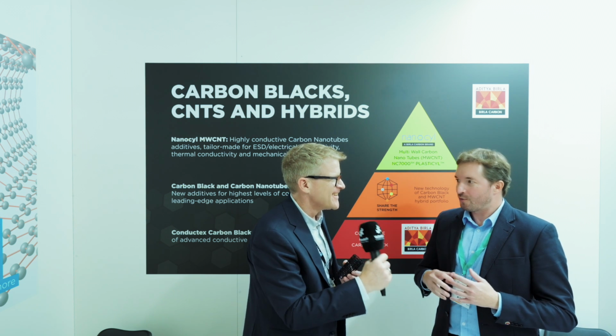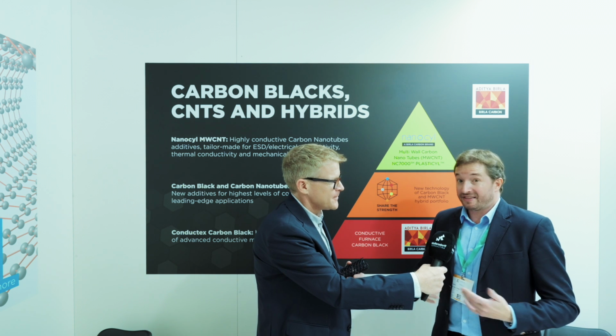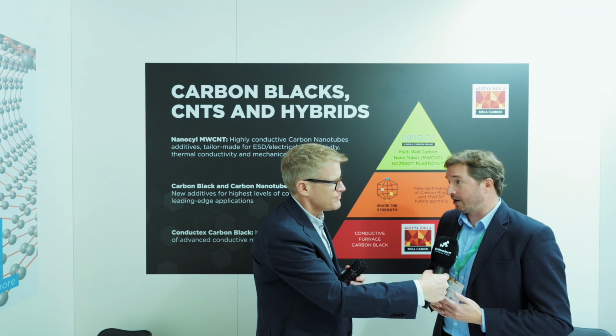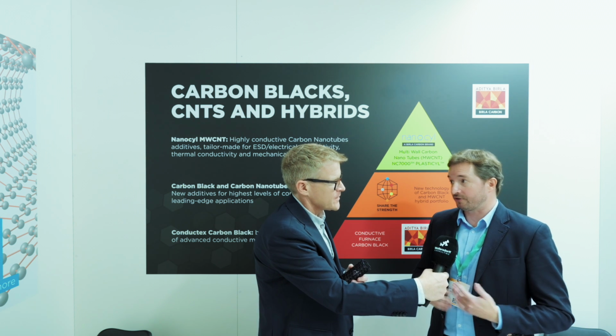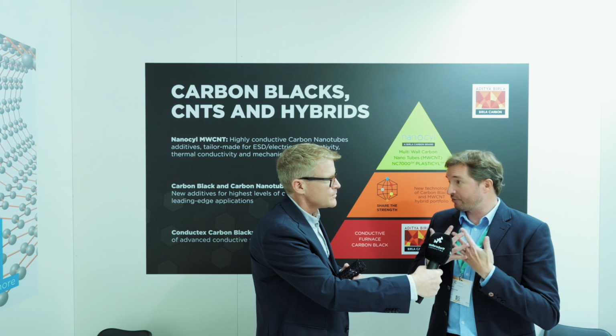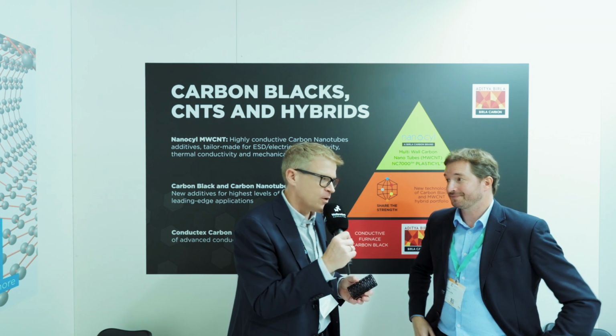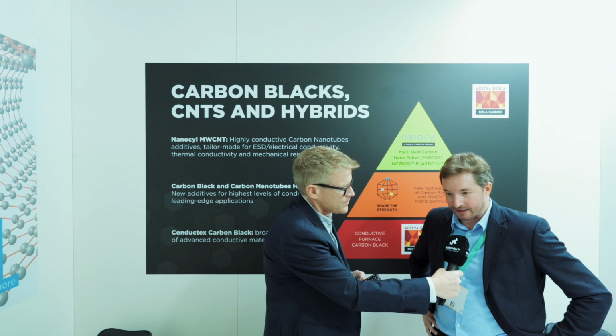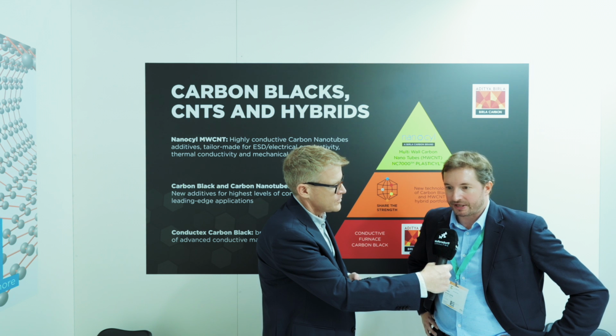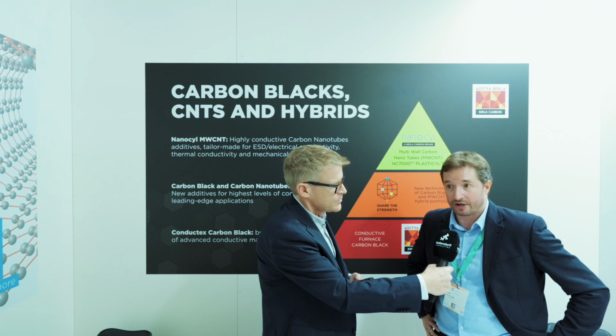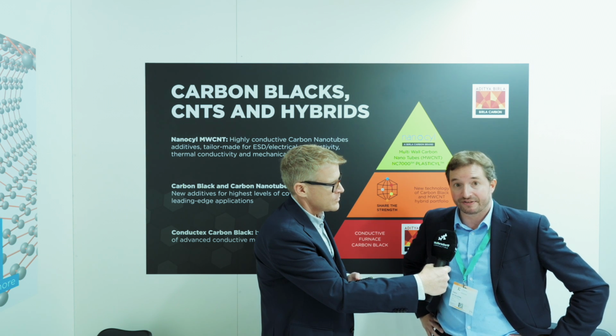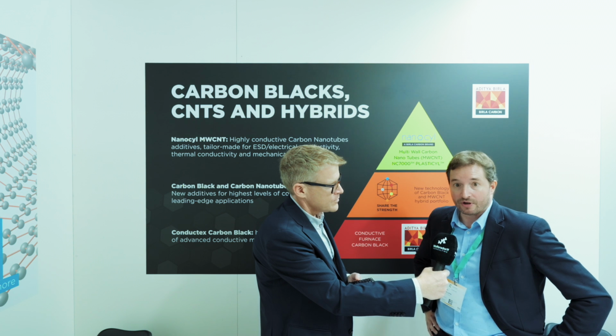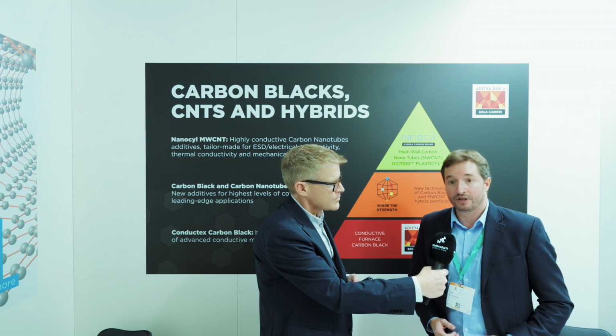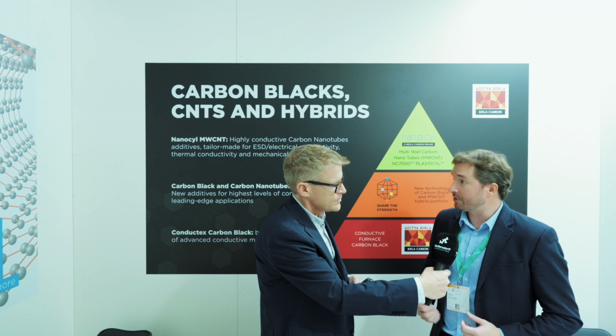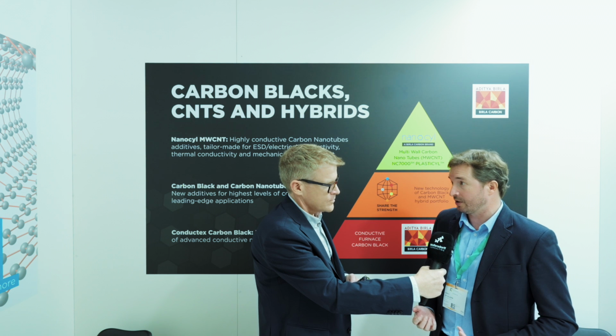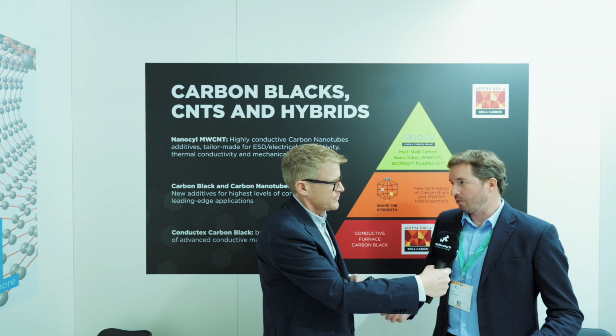Whoa. With 1 gram. So we're talking about a pretty long aspect ratio material, and this is one of the reasons why it's so effective at providing electrical conductivity, for example, because with such a material you can connect very easily through a material. You make a network through the material. You have a much lower threshold addition rate, right? Exactly. When you compare applications where you would use carbon nanotube for electrical conductivity, you would talk about much lower loading, which means that you are able either to reach a higher level of electrical conductivity or to get better mechanical properties out of your material, because you reduce significantly the amount of filler, meaning that impact strength or elongation will be much better preserved.